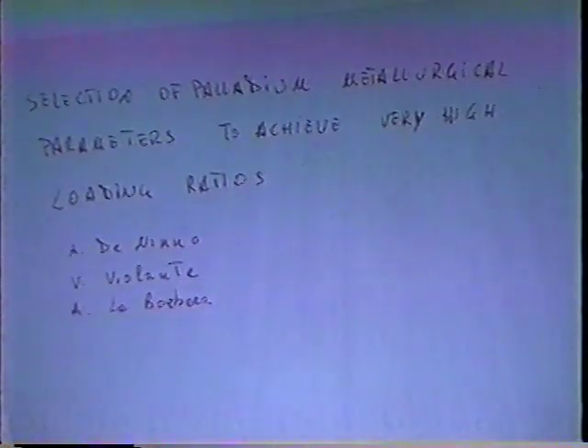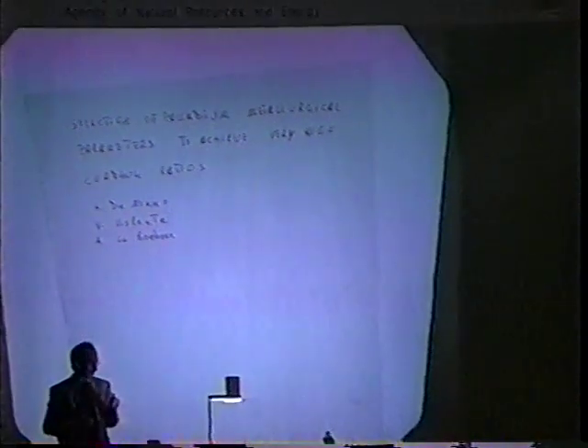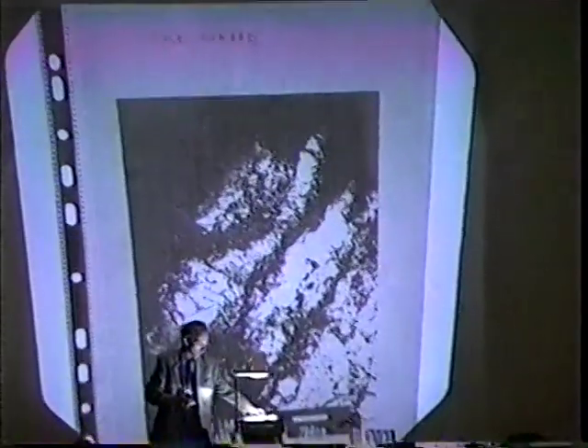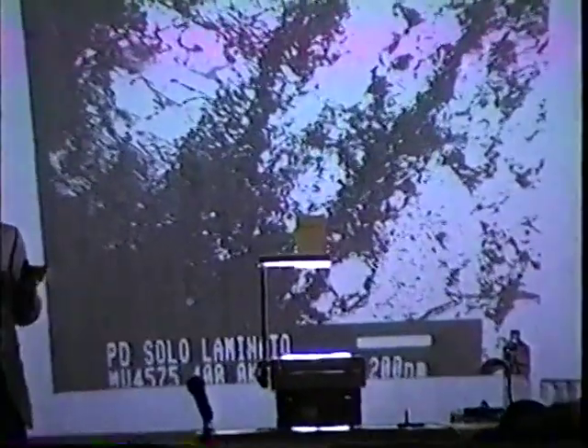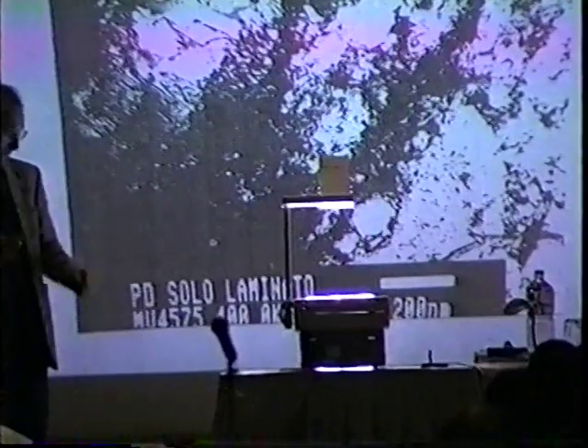So we studied the metallurgical parameters in order to reduce the effect due to the stress field which is produced when we load palladium with hydrogen or deuterium. On the basis of this concept, we performed some metallurgical treatment to materials in order to optimize the structure to have a preferential pathway which reduces the gradient concentration of deuterium inside the palladium.